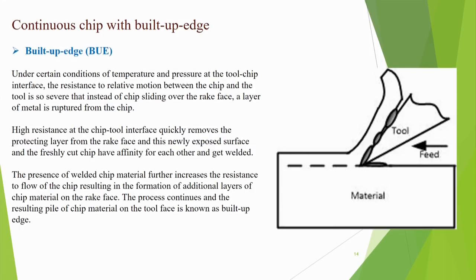Okay. Now, continuous chip with built up edge. You are seeing that here there is some built up edge, and some portion gets adhered to the chip also. This is the feed. Under certain conditions of temperature and pressure at the tool chip interface, the resistance to relative motion between the chip and the tool is so severe that instead of the chip sliding over the rake face, a layer of metal is ruptured from the chip. So high resistance at the chip tool interface quickly removes the protecting layer from the rake face, and this newly exposed surface and the freshly cut chip have affinity to each other and will get welded. Even if you have a coating, that coating will get removed and then the chip will weld to the tool surface. The presence of welded chip material further increases the resistance to flow of the chip, resulting in the formation of additional layers of chip material on the rake face.